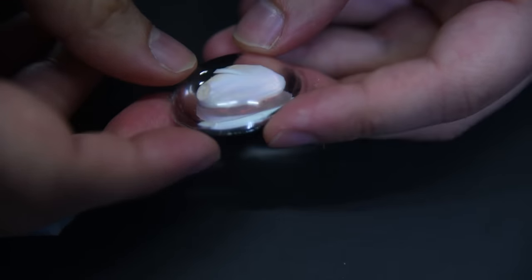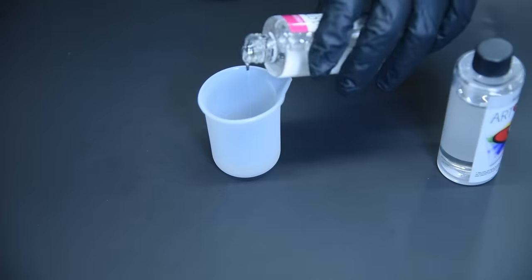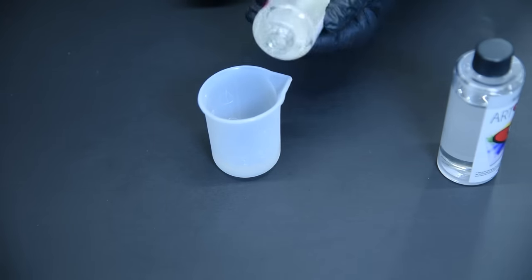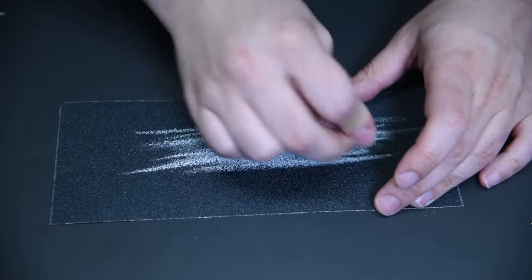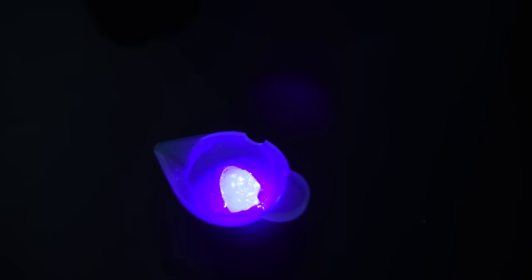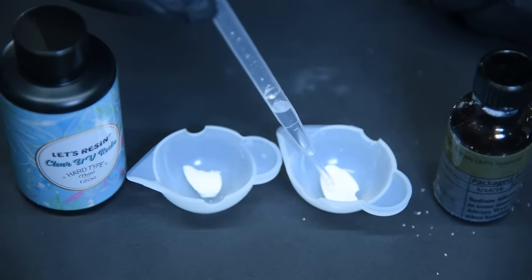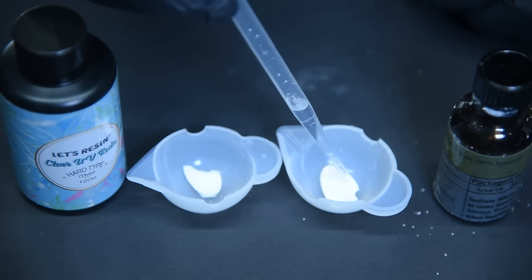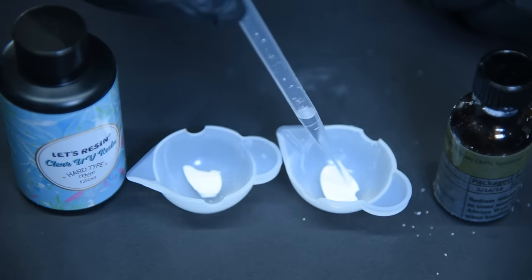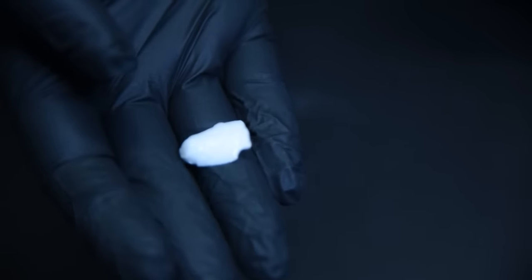The alternative is to take a page from Peter Brown's book and fill the opal with resin, but this is a treacherous task. What you ideally need is a very thin resin, but all I had on hand was UV resin and art resin, both of which are still fairly thick. Art resin doesn't actually seep into the opal structure at all, so when I went to sand away the excess, the second I hit the opal layer, a large amount of opal crumbled away. UV resin is better as it actually seeps into the opal a fair bit, but had a tendency to make the opal crack even more. I also tried sodium silicate, but there must have been some ammonia left in the opal, because it hardened on contact and didn't penetrate in, leaving a crunchy, useless shell and ruining the opal pattern.